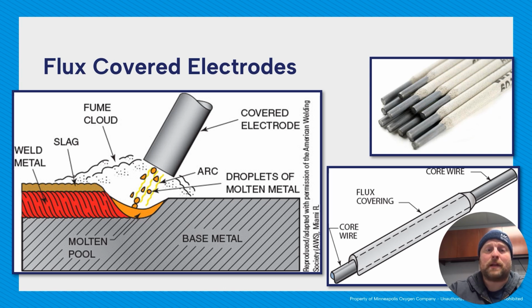Your flux covering melts, your flux goes into the molten metal, and it also creates a fume cloud to protect it, shielding gas, so to protect the molten metal from the atmosphere. And then as it solidifies, that flux rises to the surface of your weld bead as slag. It'll help to slow cooling, and it picks up a lot of corrosion, things like that could otherwise jeopardize the integrity of a weld. It can pick up a lot of that contamination and bring it up to the surface.